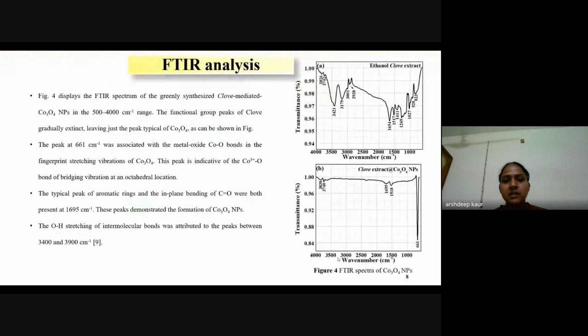For the analysis, we have done some analysis. First is FTIR analysis. This figure shows the FTIR spectra of clove extract, and the 4B figure shows the clove extract mediated Co3O4 nanoparticles. In the figure 4B, we have seen the peak at the fingerprint region, that is at 661 centimeter inverse, was associated with the metal oxide, that is cobalt and oxygen bond stretching vibration of Co3O4. This peak is indicative of Co3+ and oxygen bond stretching vibration at the octahedral location.